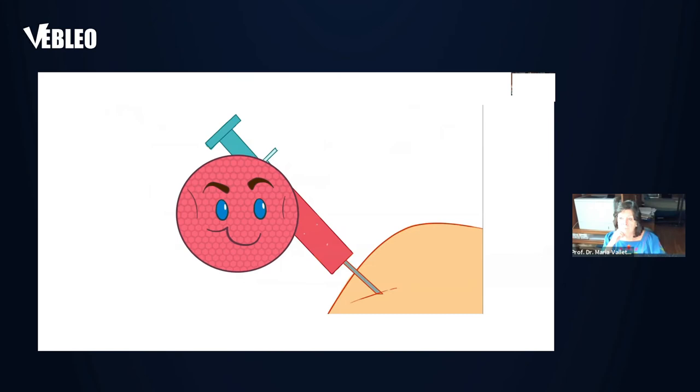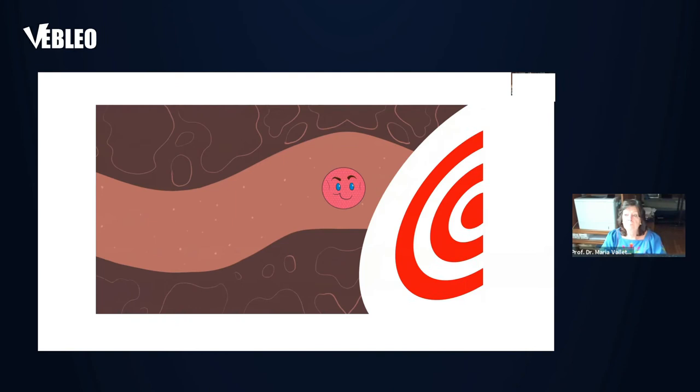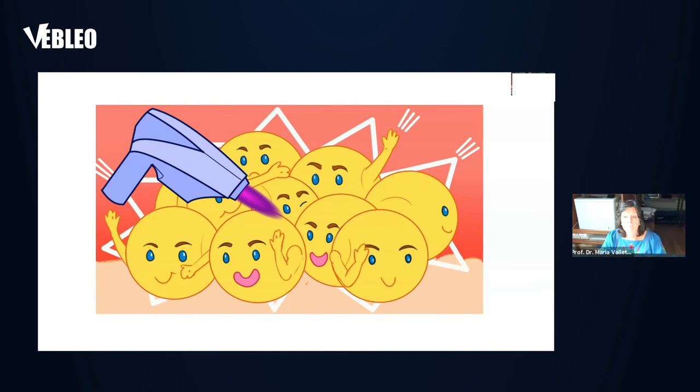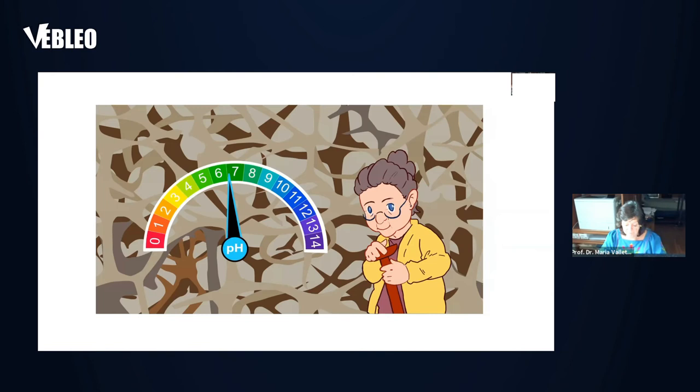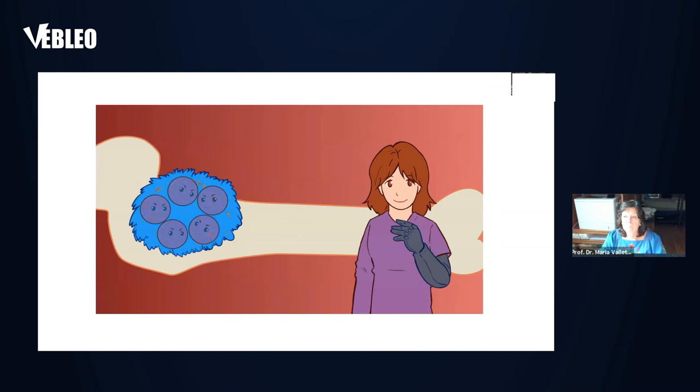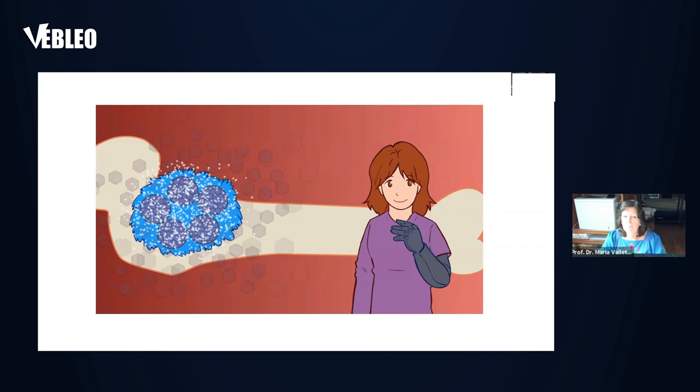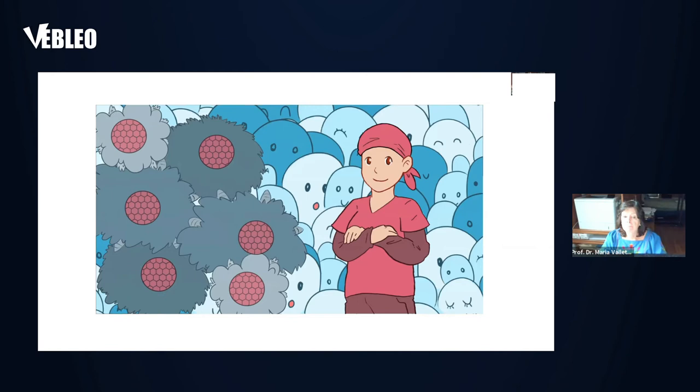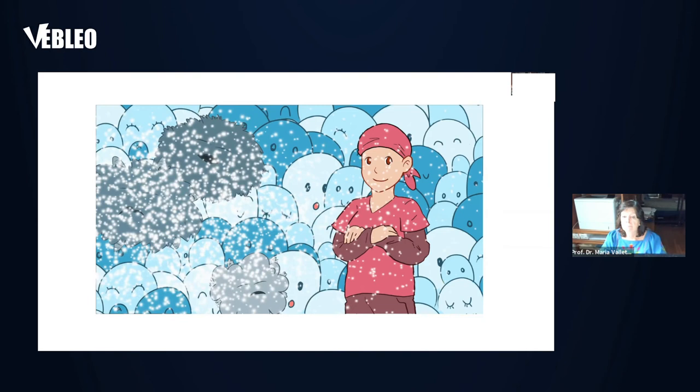The nanoparticle surface is used for coating molecular species, which allow nanoparticles to reach their target, make them invisible to the immune system, and may act as smart response-inducing stimuli. In order to prevent the unwanted early release of drugs by the nanoparticle in the bloodstream, nanocaps to block the pores or total sealing by coating the nanoparticle surface can be developed. When reaching the diseased tissue target, a suitable stimulus is applied to pop out the caps and release the trapped drug. Stimuli might be of different types: UV radiation, ultrasounds, or magnetic signals.